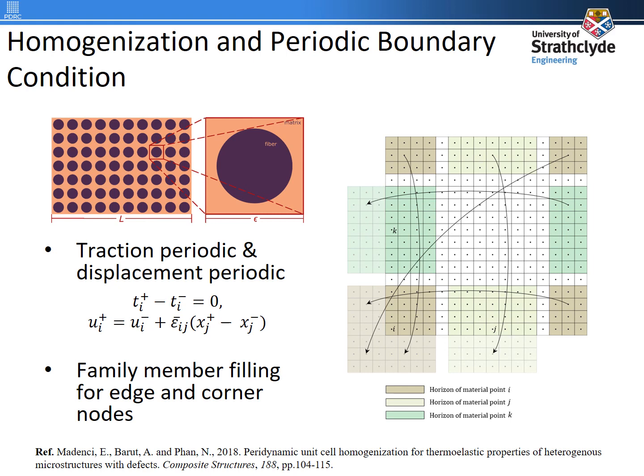So instead, we choose to perform a unit cell analysis on a microscopic structure first. This will provide us with the effective properties of the periodic material, and therefore transform the heterogeneous material, which is difficult to solve, into a homogeneous one, which can be solved quickly on most computer systems nowadays.